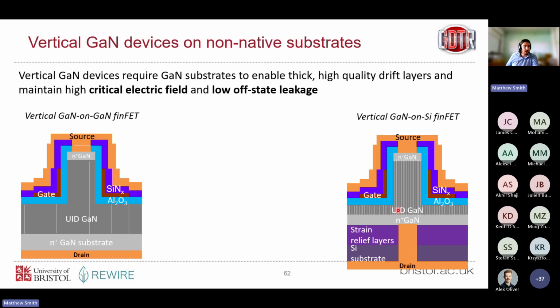So if we think about dislocations, I've drawn them as kind of gray lines here. It's much worse in our GaN on silicon layer compared to GaN on GaN. And we have the added complication that when we're on a silicon substrate, we have all these additional layers that I mentioned earlier. So we've not just got our substrate, but we've got microns potentially of strain relief layers that we have to somehow manage.